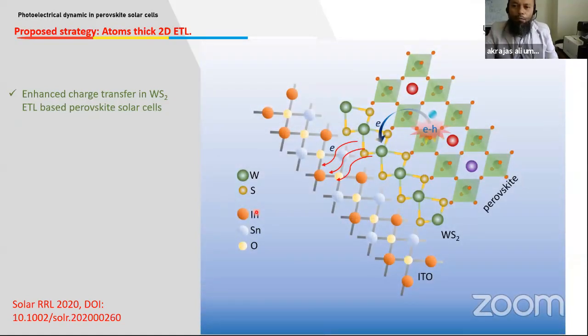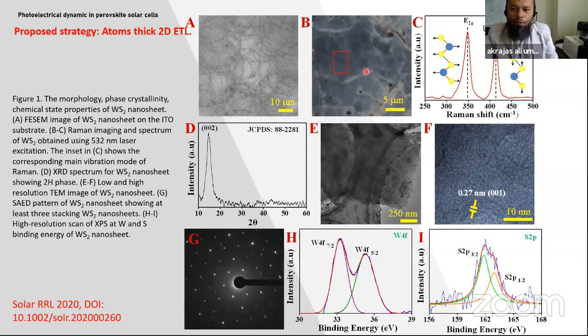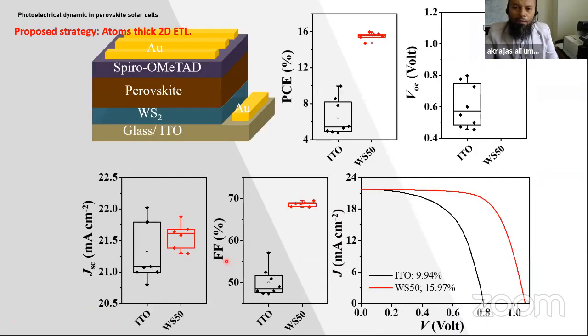This is a typical result that we recently reported, where we use a thin layer of tungsten disulfide as the electron transport layer. This is the perovskite, this is ITO, and this is a typical result of the 2D material on the ITO. This is an XRD image showing single crystalline properties, and SAED also shows the single crystalline nature of the 2D material. And this is the performance. For this condition, we get efficiency up to 16% because this structure is very thin. To avoid the contribution of ITO, we compare the performance with ITO, and the device with tungsten disulfide is much higher. So we can say that this material can function very well as an ETL.